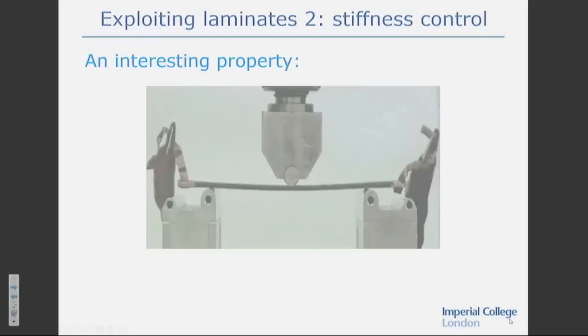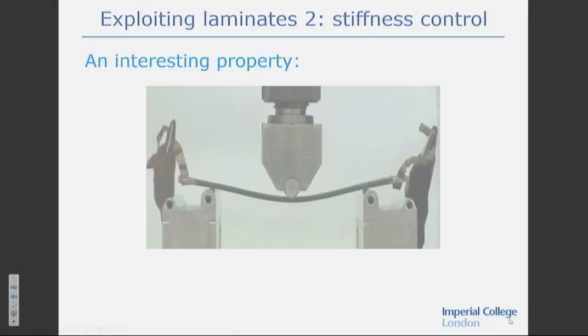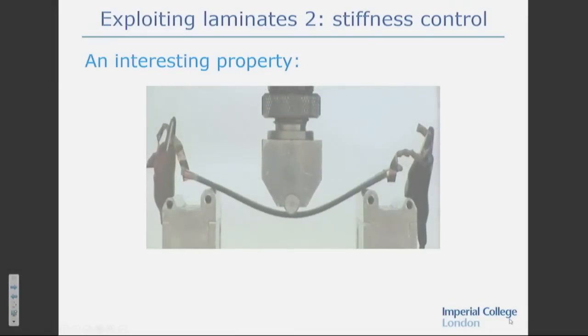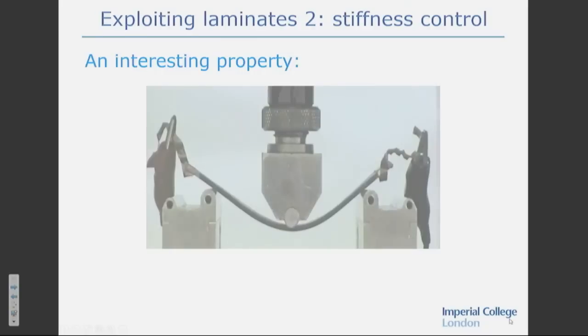But there's something else interesting about this material that we realized when we were testing it, and it's shown in this video. Just before we do this, a lot of the work we've done is taking this material and putting it in an environmental chamber. But of course, we're interested to know how we can actually heat these in practice. In this case, you will see we've got things connected to the end. They're actually electrical connections to the end of the specimen, so we can use the fibers as heating elements in their own right, resistive heating. So we've heated this specimen up, and we do the bending test. And you can see it deflecting, and actually deflecting hugely. You wouldn't get anywhere near this if it wasn't at this temperature.